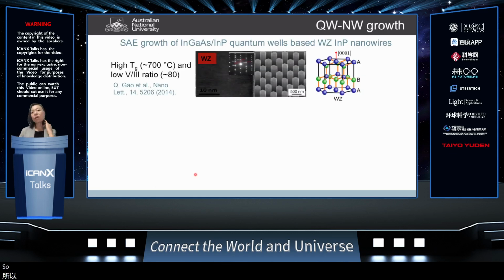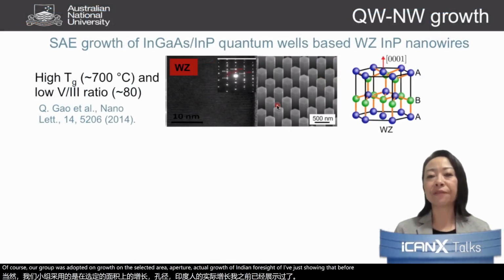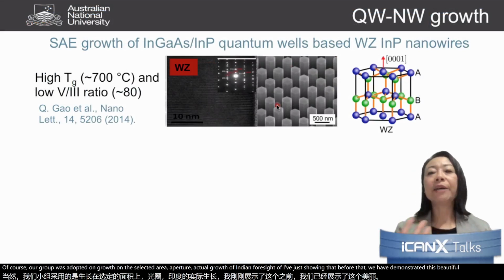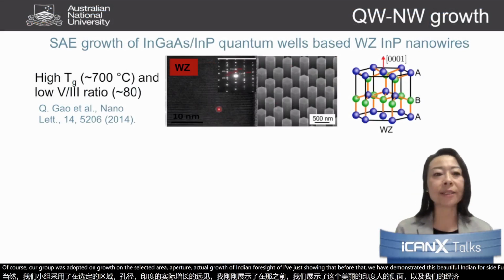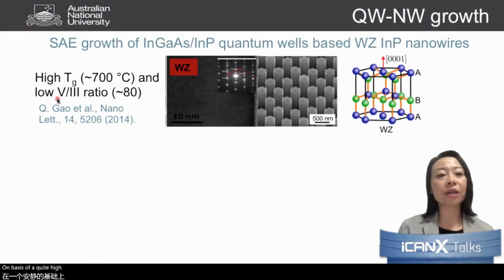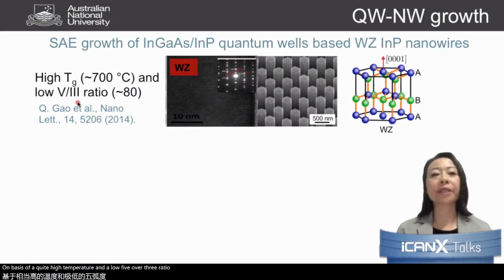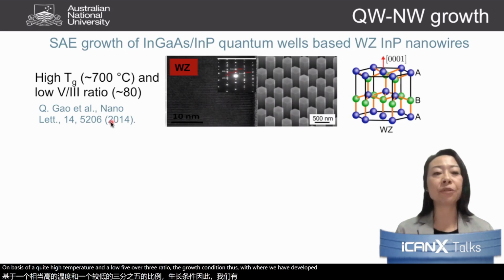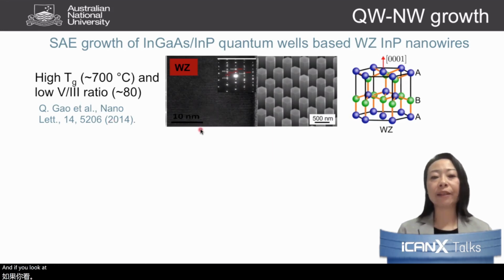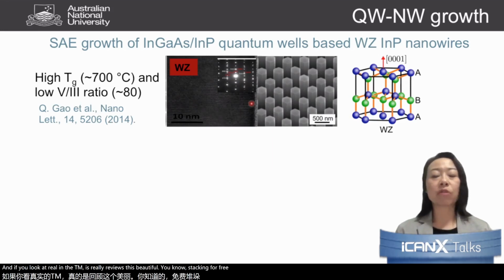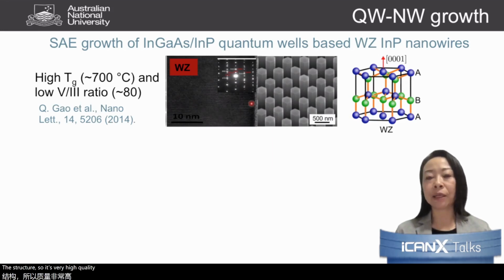So of course, our group started our growth on the selective area epitaxial growth of indium phosphide. I've just shown you that before, that we have demonstrated these beautiful indium phosphide quantum nanowires based on a quite high temperature and a low V/III ratio growth condition. That's what we developed in 2014. And if you look at the TEM, it really reveals this beautiful, stacking fault-free structure. So it's very high quality indium phosphide.